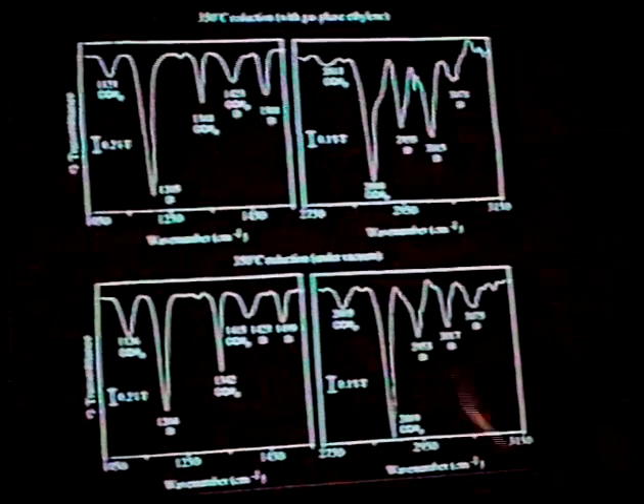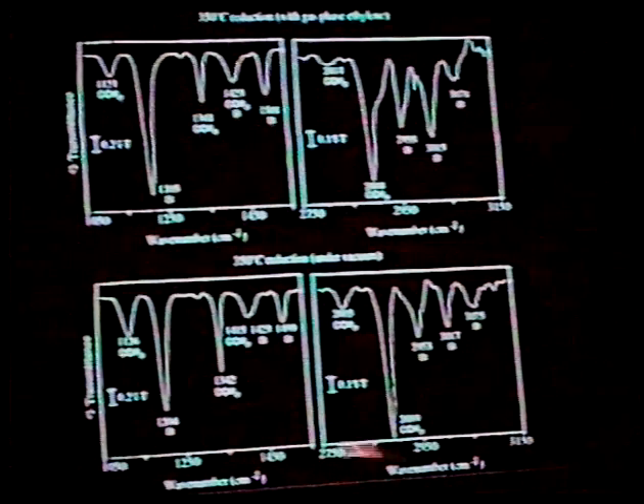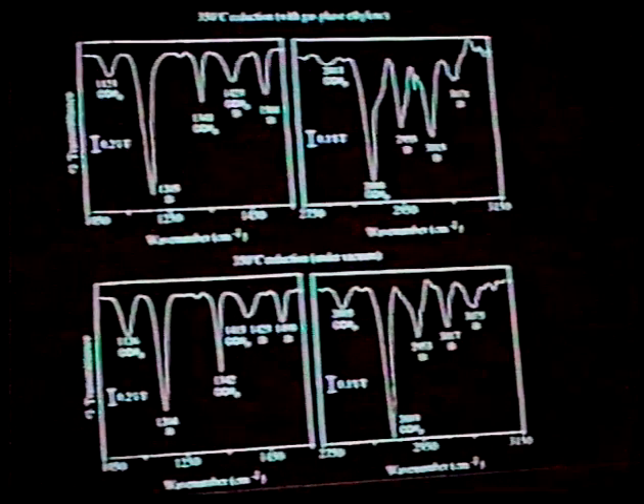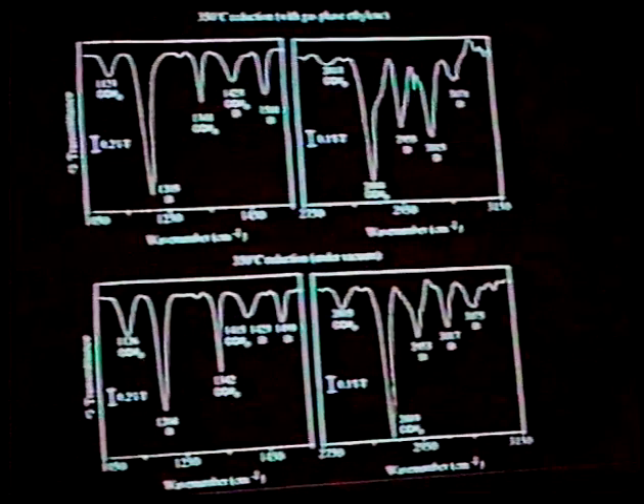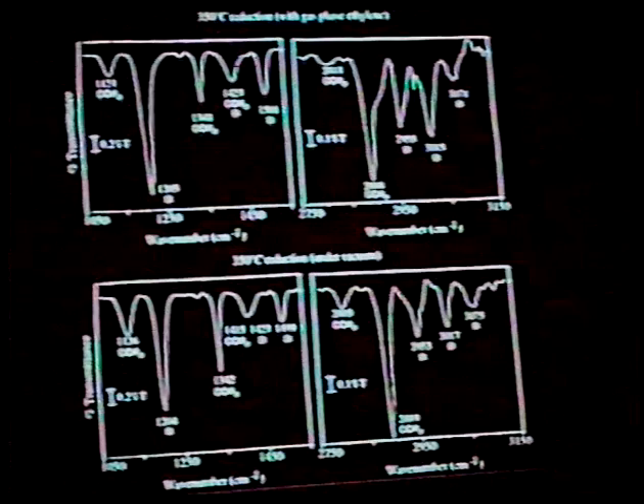But what we have now is, again, an indication that the pi-bonded species appears to be sensitive to these pretreatment conditions, whereas the ethylene, or the sites that are responsible for forming ethylene, are unperturbed. They're unaffected, at least as far as this type of measurement goes, in responding to this different pretreatment. So what we have now is two different kinds of sites that do different kinds of chemistry, and they appear to do these different kinds of chemistry independently from one another.